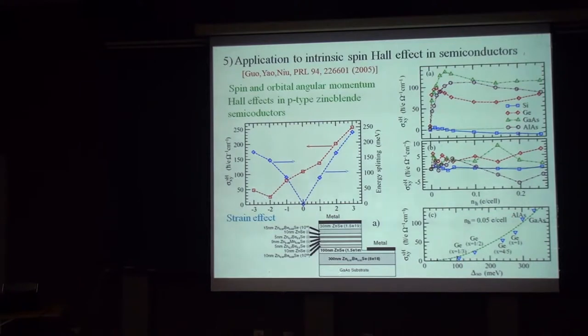Now, this diagram answers the third question about strain effect. As I said before, when you apply strain to a semiconductor, this Dirac monopole singularity will be removed. You open a gap. You can see, if you apply tensile strain, the gap opens. If you compress the semiconductor, the gap also opens. However, spin Hall conductivity does not disappear. It's still there. So, this basically answers several questions I mentioned before.